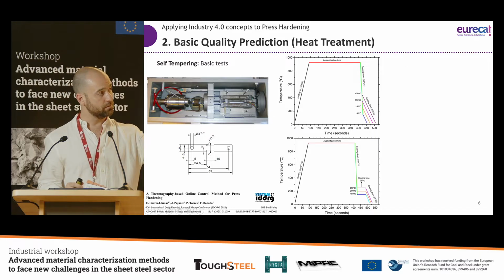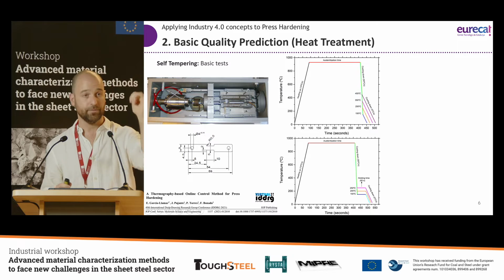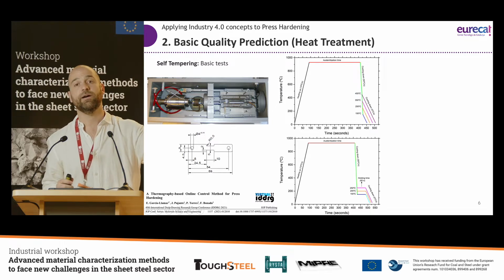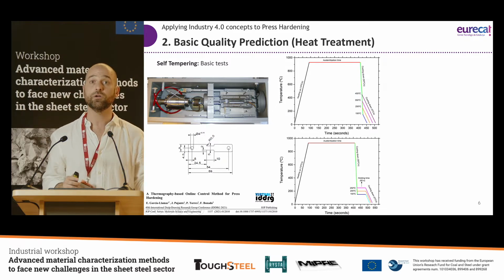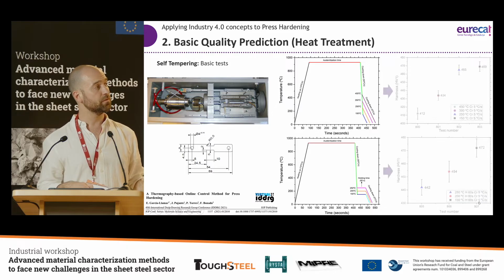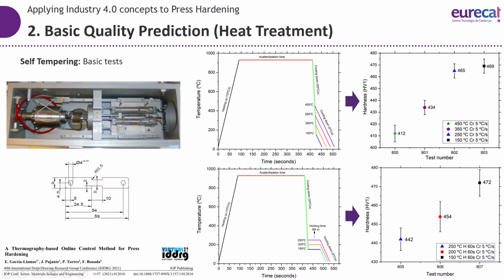And we took these temperature cycles where we would interrupt the quench and then cool slower, 5 degrees per second, 10 degrees per second, which is more or less air cooling. And once we do that, the results will not surprise anyone, but of course, if we interrupt the quench at high temperatures, what we get is less hardness. And we get a microstructure that is no longer fully martensite, or martensite with a little bit of bainite, but rather some tempered martensite, some tempered bainite, some even Widmanstätten phases in there. This is something that in retrospect makes sense and that we could actually expect, but okay, it was nice checking that.